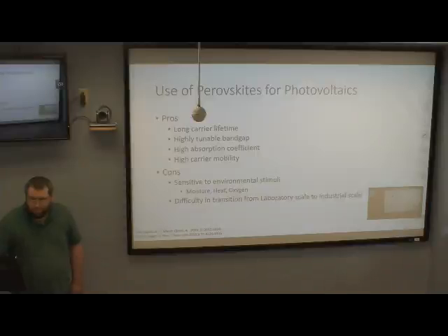and their gaps are in UV, right? Yeah. So they may absorb or emit, but it will be in UV and it will not be useful for technology. And the precursors are fairly toxic to the environment as well, at least in the lead halide perovskite cases that I'm looking at right here.